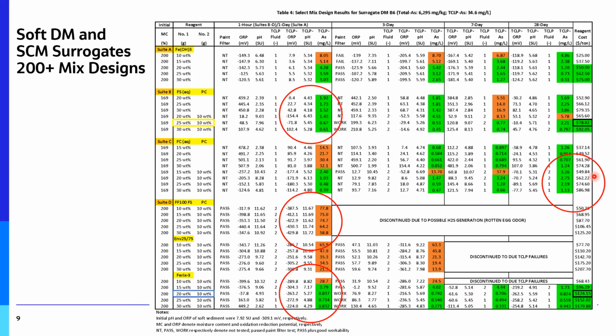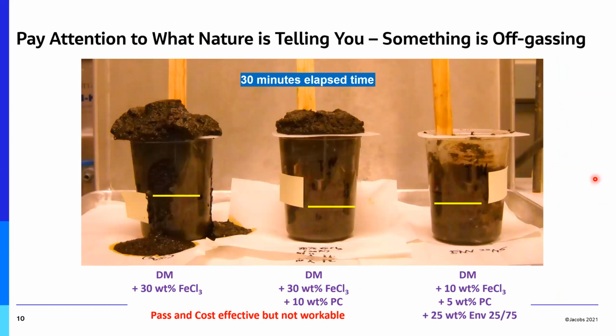What was also quite interesting was we used ferric chloride, which is from the steelmaking process, right? And that is also an iron salt and has lots of iron in it. So it was comparable to the ferric sulfate, but actually cheaper. So we ran that through the system. And what we found was, in fact, that was actually more cost effective, but you have to pay attention to the workability. And so let's talk about that for a minute.